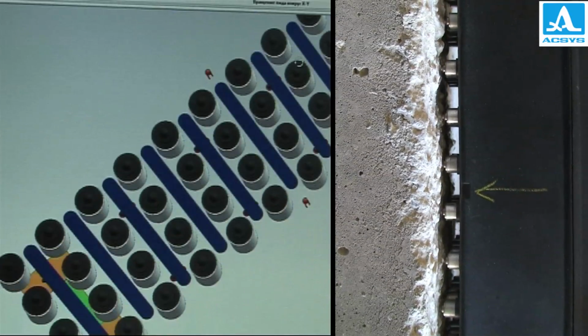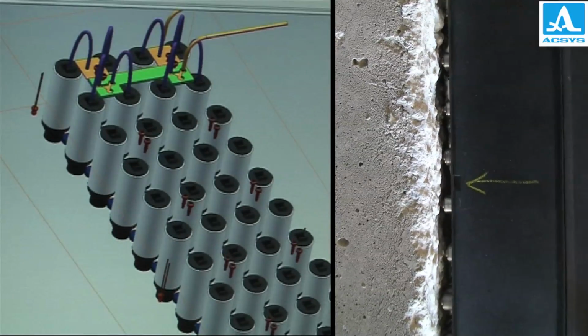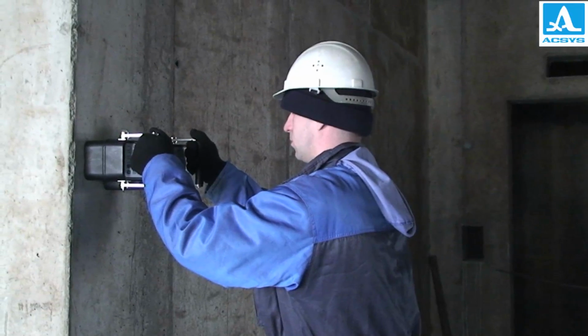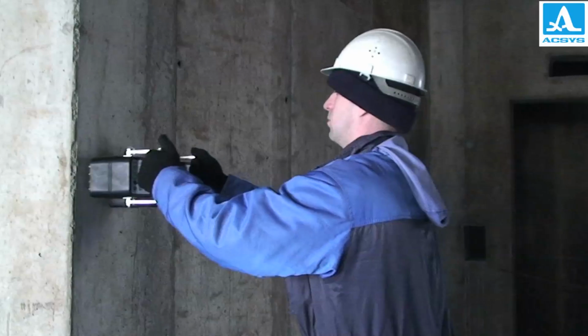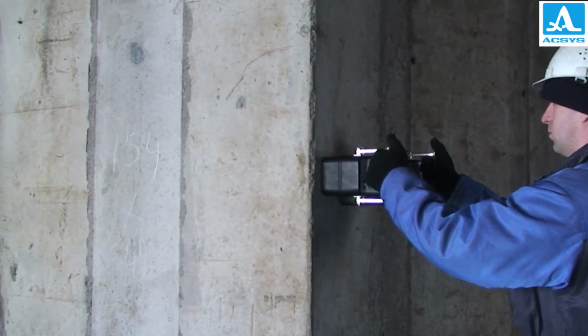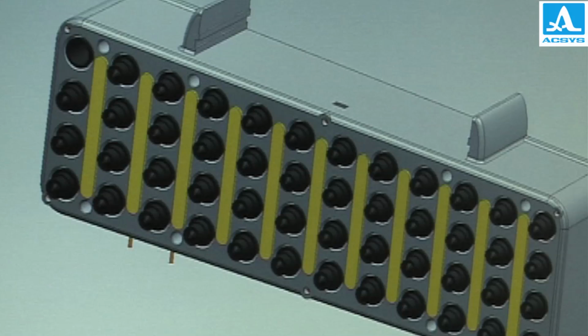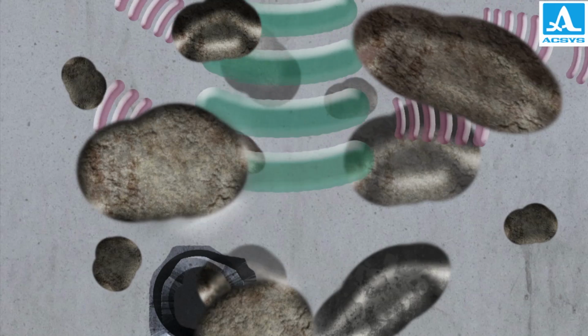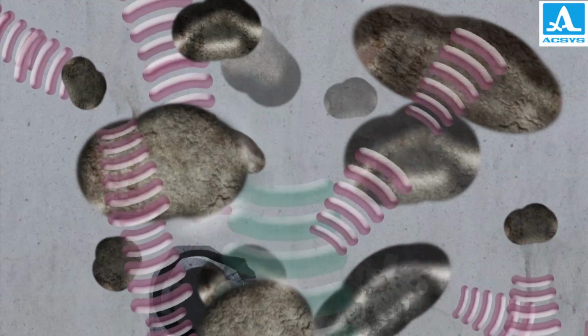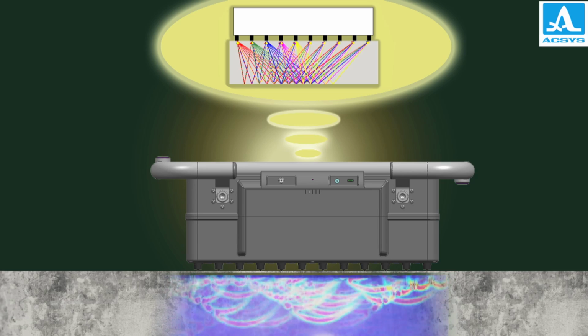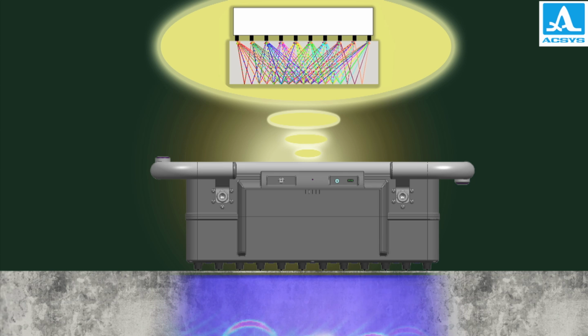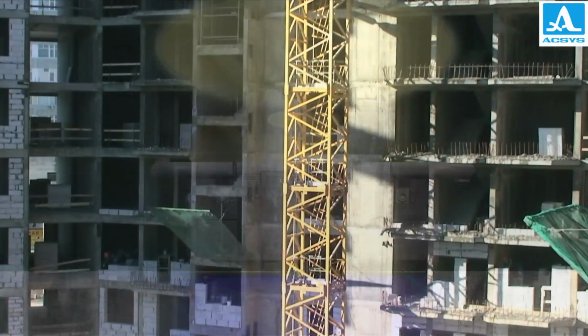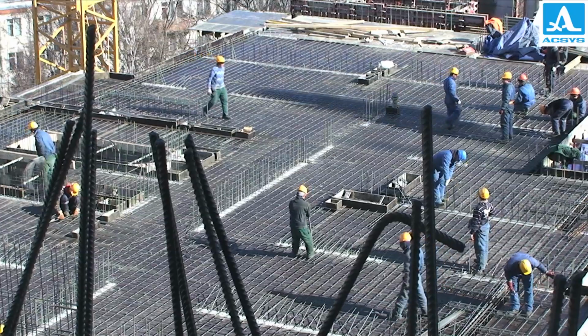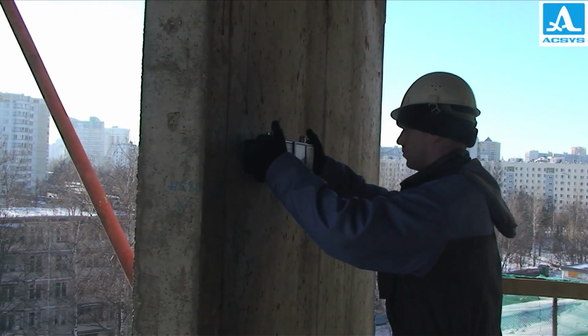The use of multiple transmitting and receiving transducers electronically connected in a single array provided the much-needed ability to conduct one-sided tests. Experimental tests have shown a maximum depth of penetration of about 2 meters. The large area of the array provides a constant reception of the reflected waves. During the time of a double pass through the concrete structure, the ultrasonic wave partly scatters and gets absorbed, but the echo signal fixed not by one, but by 48 highly sensitive elements visibly stands out against the background of occasional re-reflections. The MIRA instrument can be used as a one-sided test method to investigate problems in high-rise building facades, tunnels and underpasses, highway pavements, bridge decks, etc.